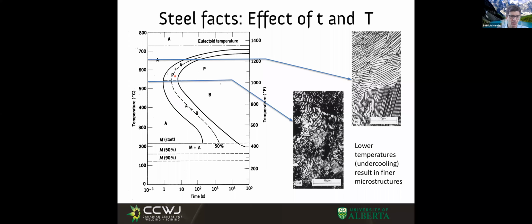Because now it's at a lower temperature and diffusion is much slower, the transformation requires smaller spaces and we have finer microstructures. Just to make a mental note, in welding, we typically like small grains. So if we have transformations at high temperature, that will end up with coarse grains. When we have transformations at low temperatures, we end up with fine grains.